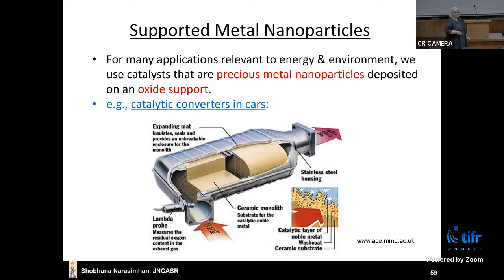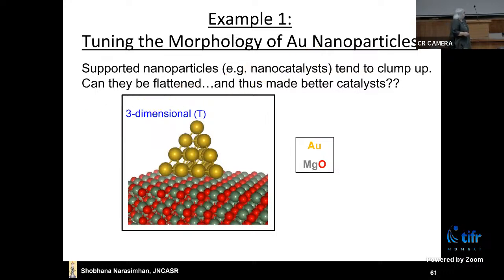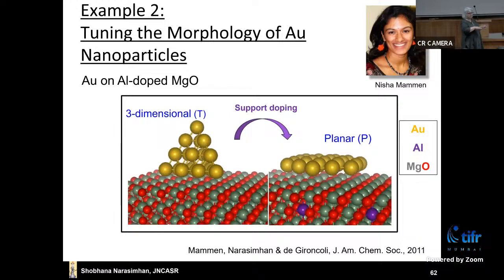Okay, so for these reasons, one wants to study systems like this. So the first question here, which we asked, is whether we can change the shape of the nanoparticle. Okay, so here, there's another whole weird thing there, which is that you use gold often, and I'm not going to say why, but here, if you put a nanoparticle of gold on, for example, an MgO surface, it forms this clumped up structure. In this particular case, it's formed this tetrahedral pyramidal structure. But what one would prefer is that it form such a flat planar structure, because you believe that it will be a better catalyst. And the question is, how do you make it change the shape?